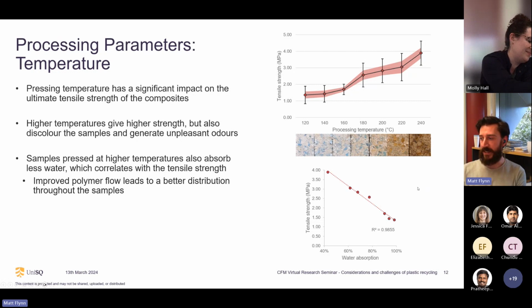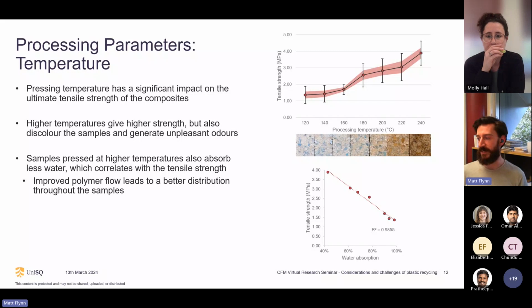We also get a decrease in how much water is absorbed at higher temperatures. So this is because the polymer is flowing and it's sort of encasing the paper and stopping that water absorption. And this is, as we see by this correlation, quite closely related to the same properties that are imparting that increase in tensile strength.